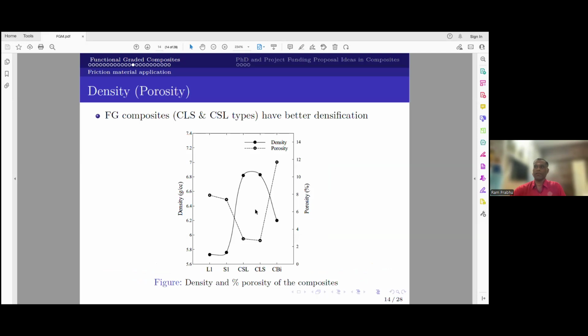And interestingly, the FG composite has good densification. One reason is that this high density is attributed to the copper layer also, because copper has a higher density. But we also measured its porosity. We see that it has less than 3% porosity compared to the conventional composites, which have somewhere around 8%. Bimodal has not worked out. It is between these two, the conventional and the functionally graded composites. In other words, we have material and particle size gradient. Without that, if I have only the compositional gradient, that gives a density between the conventional and the functionally graded composites.